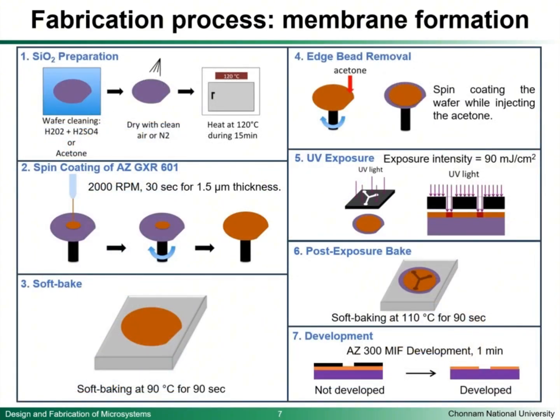So for the photolithography process, the first one is to prepare the SiO2 that we already prepared before, and we will utilize dry and also wet cleaning to remove the moisture and also the dust, and heating for some time at 120 degrees Celsius. And the second one will be the spin coating to achieve the desired thickness of 1.5 micron, and we can achieve it with 2000 RPM for 30 seconds. And then we will soft bake it at 90 degrees Celsius for 90 seconds.